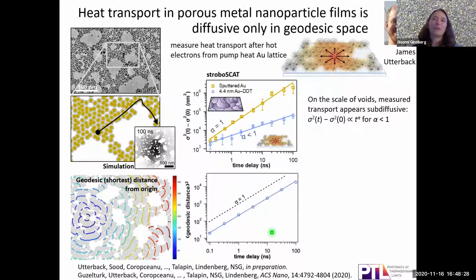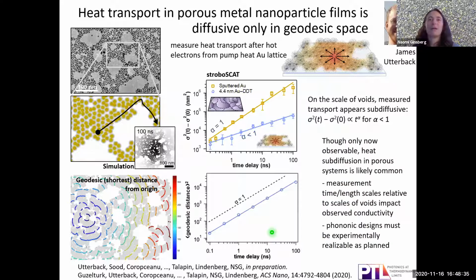So this is a cool result, in my view, not only because it wasn't previously possible to spatiotemporally resolve this impact of disorder, but also because we suspect that this subdiffusive process, even though it's scarcely been measured, is really quite common. Unfortunately, that means that more conventional heat transport measurements, which people use in bulk, will give a different answer depending on the length or time scale on which they're done, which could be especially concerning for, say, nano or microstructured devices if they contain imperfections. But at least now we know.